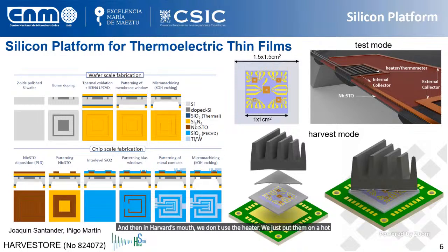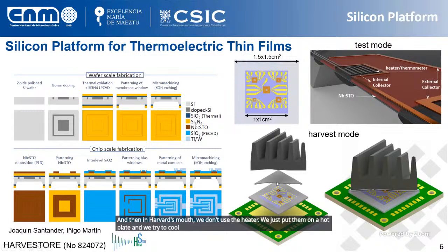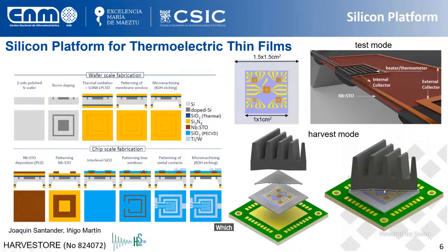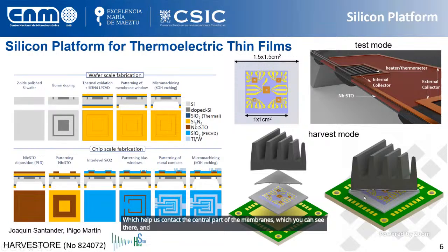And then in harvest mode, we don't use the heater. We just put them on a hot plate, and we try to cool the central part of the membrane with special adapters that we design and fabricate in silicon, which help us contact the central part of the membranes, which you can see there, and produce or maximize this temperature gradient.